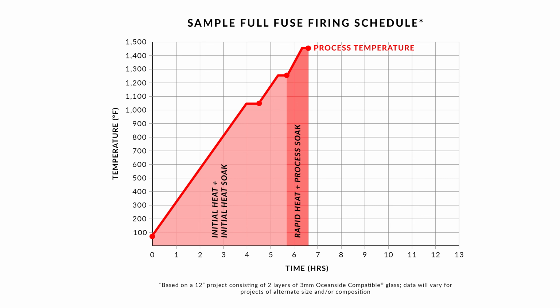For a 12-inch project made with 2 layers of Oceanside compatible 3mm glass and aiming for a full fuse, the rapid heat and process soak segment would increase the temperature at a rate of 300 degrees Fahrenheit per hour, up to 1465 degrees, and hold it there for 10 minutes.